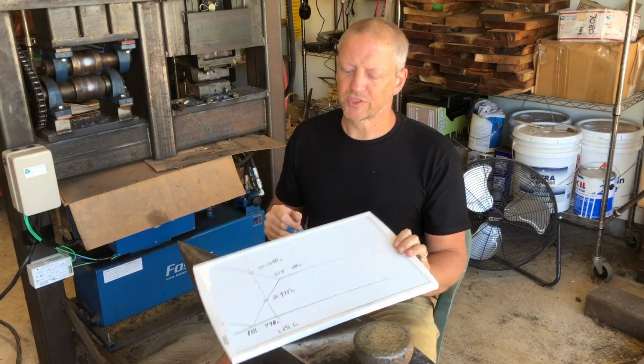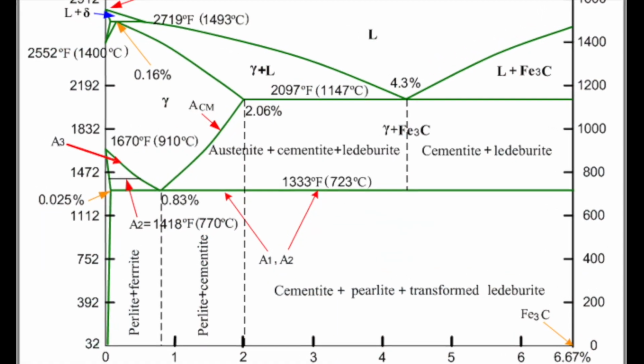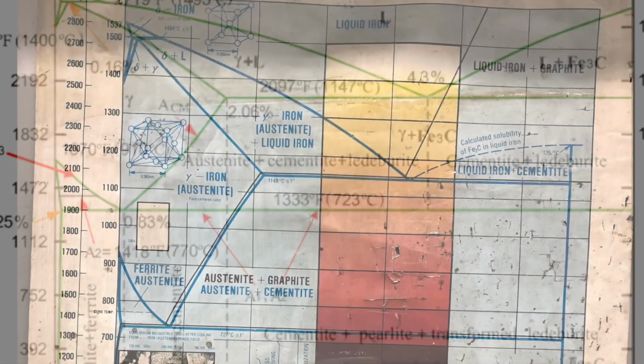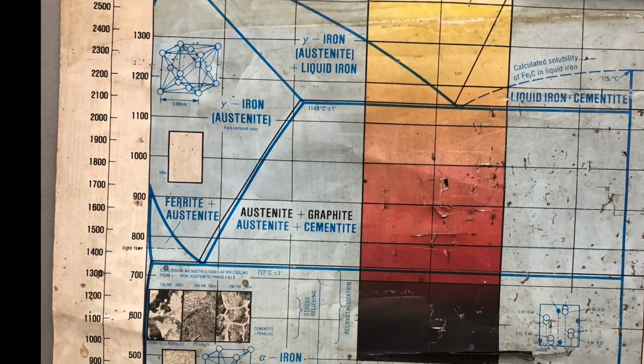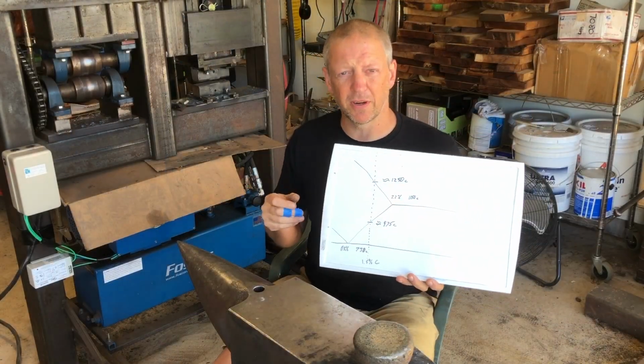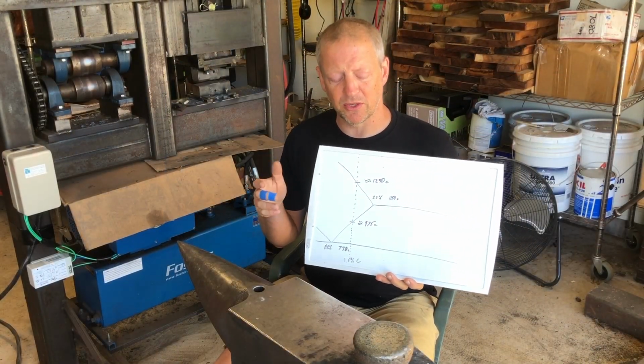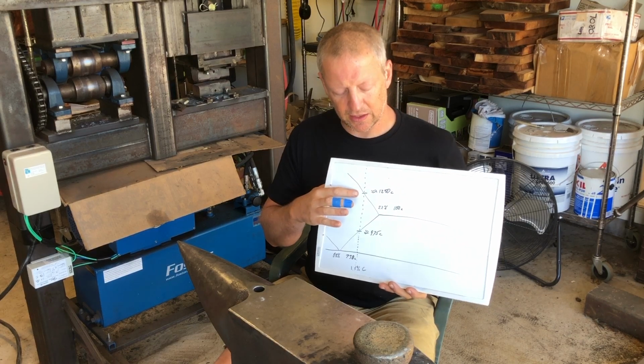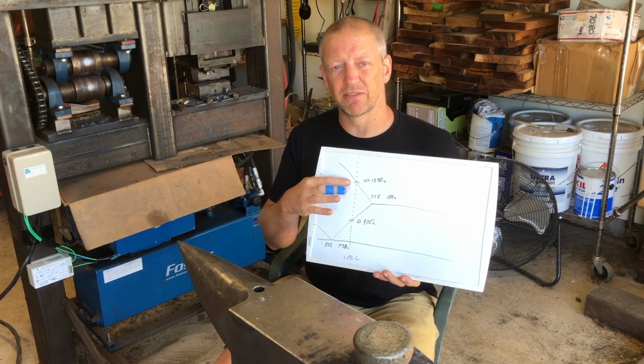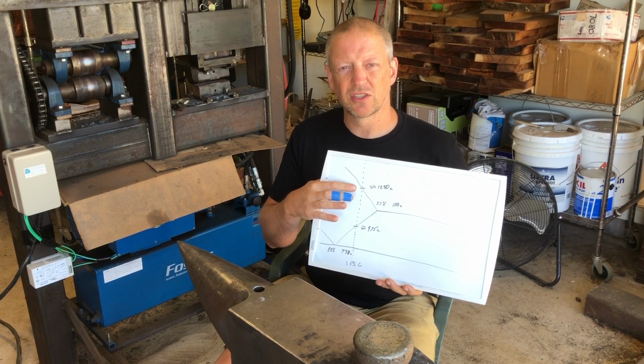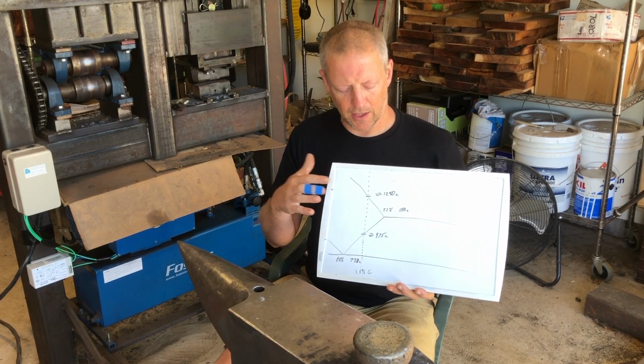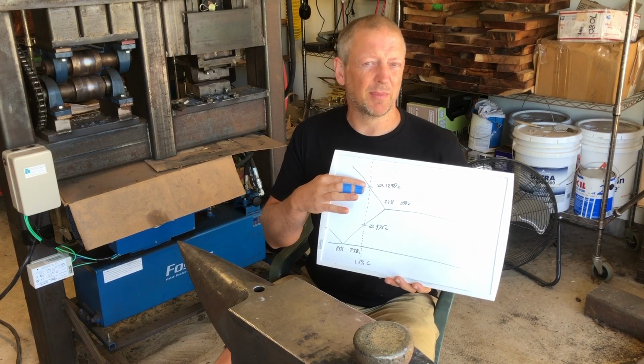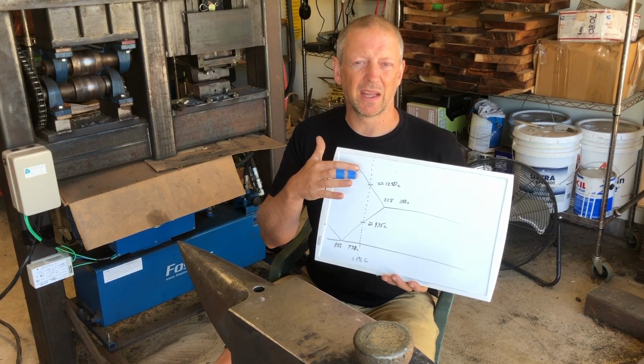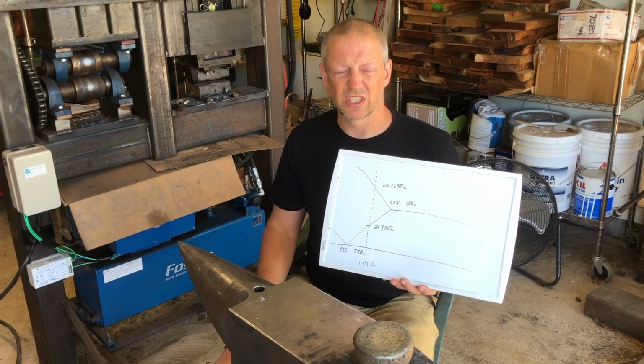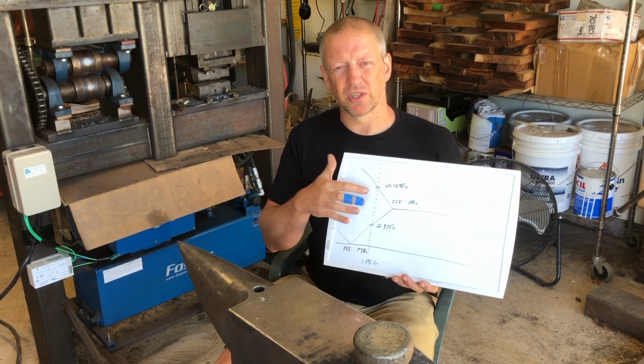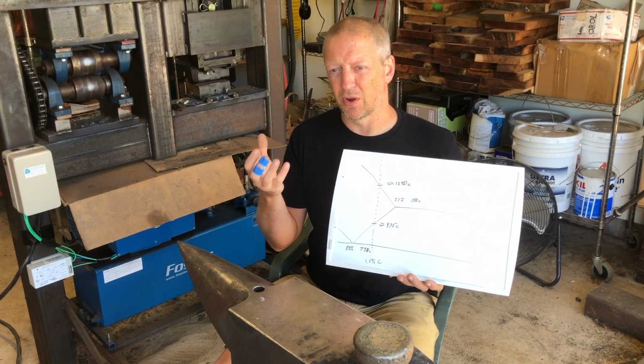So, to the roast. I've included two versions of the iron-carbon phase diagram to help illustrate the discussion of the roast. Now, referring back to some of Pendray and Verhoeven's work, at least at one point in time, they were actually doing a very long roast at 1250 centigrade. And that is really the limit of what you can do before you start going back into the mushy zone or slushy zone of having partially melted material.